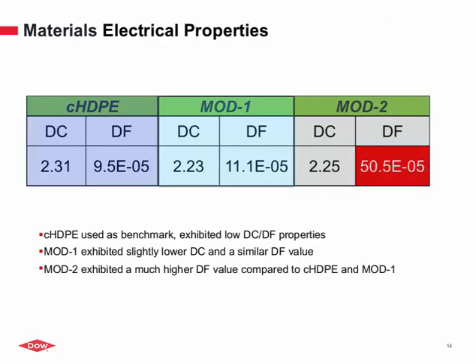From an electrical standpoint, the control has a typical dissipation factor and dielectric constant of what is common for these systems. The modified system 1 has a slightly lower dielectric constant, which is in the positive direction, and the dissipation factor is more or less equivalent to the control. Modified 2 has a slightly lower dielectric constant, however, the dissipation factor was much higher compared to the control.